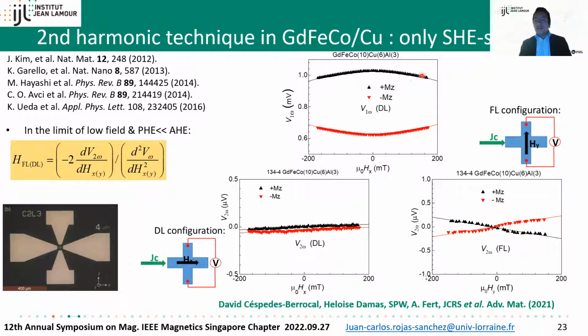The first harmonic shows a parabolic behavior. The second harmonic is a linear one. In the damping-like configuration, where the in-plane field is along the current, we observe that the slope doesn't change with the initial state of magnetization, while in the field-like configuration, where the in-plane field is perpendicular to the current, the slope changes depending on the initial configuration of the magnetization of gadolinium iron cobalt in our case. So we can quantify it, it's not difficult.